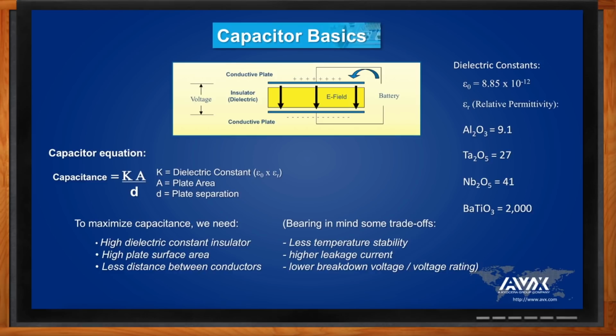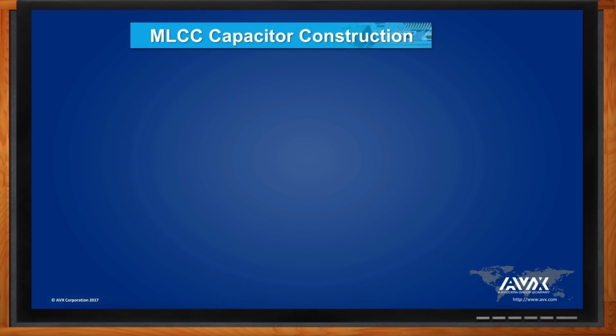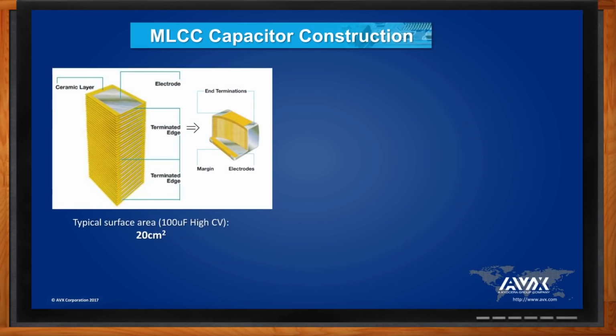I see the difference is dielectric constants. So how do these different technologies maximize the area and minimize the distance? Yeah, so again, if we start off with the ceramic, which is a regular multi-layer component, that area, if you're going to the number of plates we have inside for a high capacitance part, like 100 microfarads with 800 plates, you're talking about 20 square centimeters in something like a 1206 size chip.